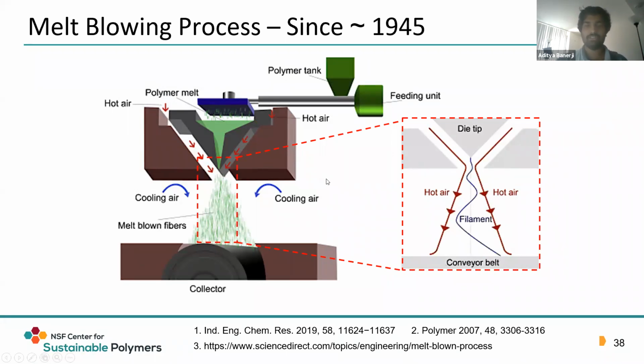Melt blowing has been commonly used in industry for about half a century now. It operates by feeding the polymer through the hopper at the top, and once it passes through the die, it is melted at high temperature above its glass transition or melting temperature, then extruded through the die tip. Hot air jets, marked by the red arrows, stretch it out into thin filaments, leading to further thinning and reduction in diameter, which during flight cools down below its solidification temperature and is subsequently collected on the rotating drum below. The inset on the right highlights the mechanism by which this process happens.